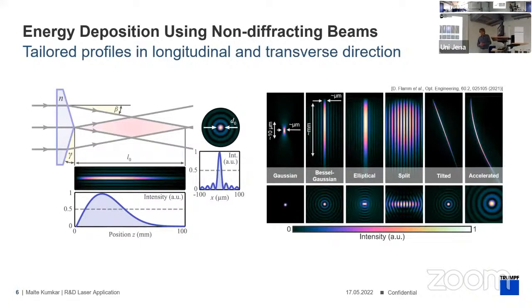but you can generate other non-diffracting beams, and this may be useful. For comparison, you see the Gaussian beam on the left side. So typically for tight focusing, in order to generate the nonlinear absorption, then the length is in the range of 10 micron, and makes no sense for full thickness modification. But the Bessel-Gaussian beam has a circular symmetry, and often it's better to have an elliptical symmetry of the beam, or to split it in order, in principle, to generate in a single shot more lines, or to have it tilted in order to get beveled edges, or even accelerated. And everything can be done, and one has to find out what works for inscribing modifications suitable for separation.